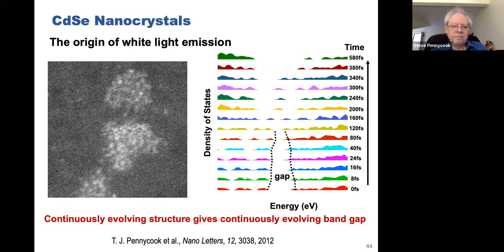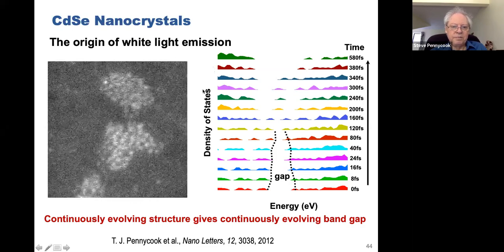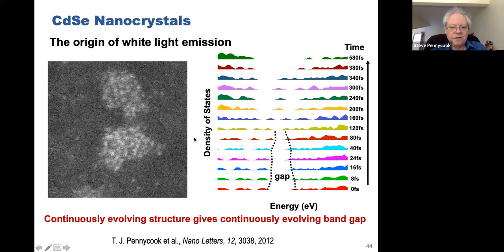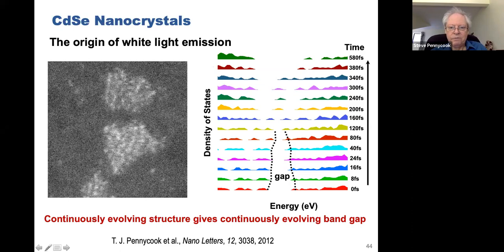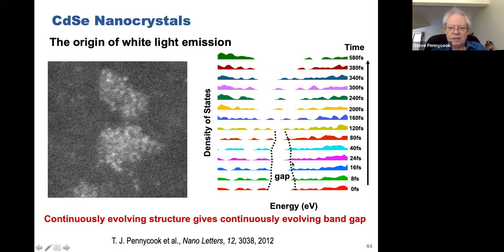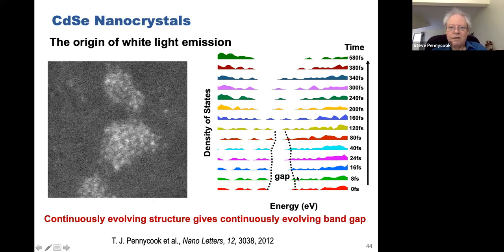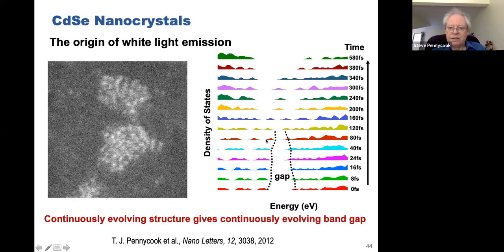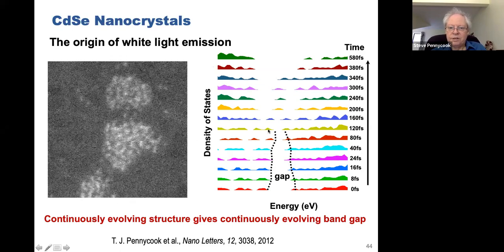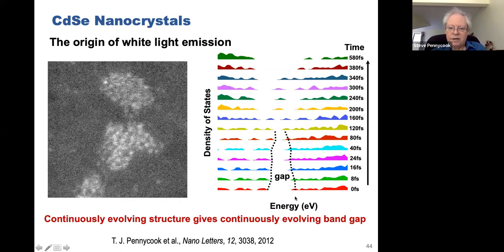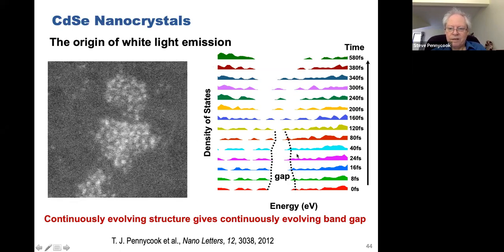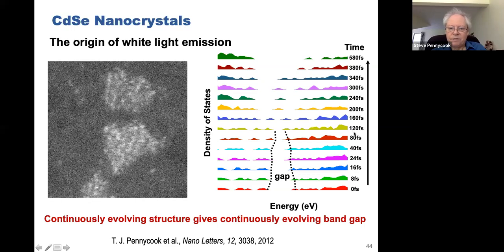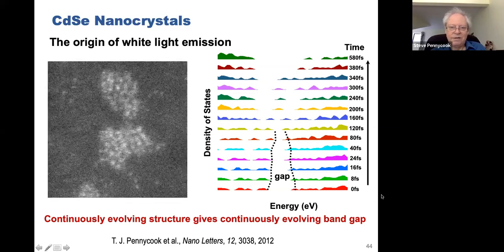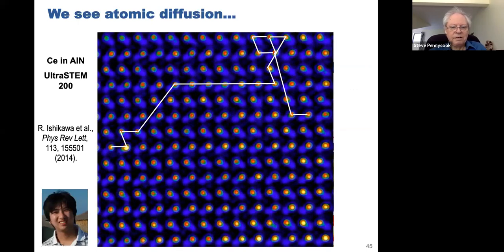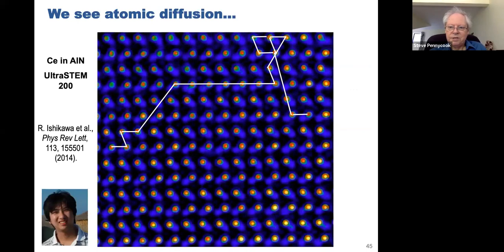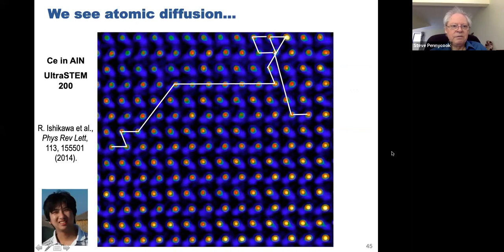And when you put them in the microscope, or when Tim put them in the microscope, this is what he saw. No fixed structure, they were continuously evolving, and he was able to do the DFT and showed that as it evolved, again with quantum molecular dynamics on a cluster, he could show that those fluctuations, he heated it up to about 500 degrees, and again got this white light emission as an average over time. Rather satisfying result there. Ryo Ishikawa was also sent by Yuichi Ikuhara as a JSPS fellow.